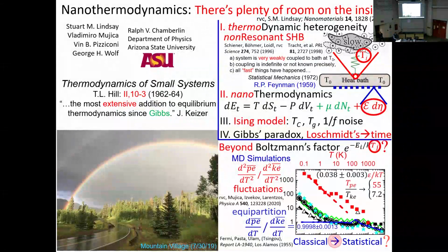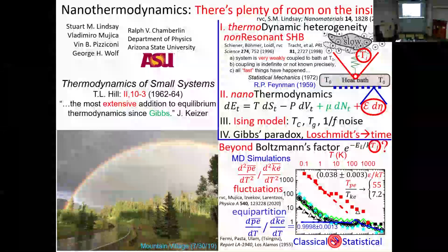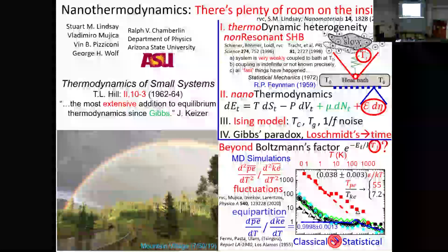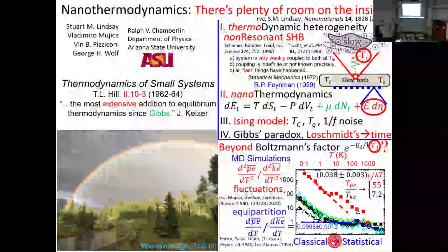The best way I can answer that is from the molecular dynamics simulations. These extra fluctuations come from atoms that are not at the bottom of the potential well, they're on the side of the potential well. So the anharmonic terms come from second neighbor interactions that are not at the bottom of the well, they're on the side of the well. If those atoms move coherently, their anharmonic effects will cancel, but they don't. And so all of this extra fluctuation comes from those second neighbor and third neighbor interactions. So it's not purely harmonic. There are some anharmonic terms that localize some of the fluctuations somehow.